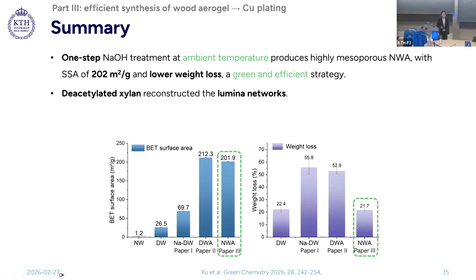Different from the reported wood aerogel fabrication studies, here we demonstrate that the deacetylated xylan migrates from the cell wall and reconstructs the lumina fibrils during the treatment. As the application demonstration, copper-plated wood aerogel shows favorable electrochemical performance due to the copper-coated lumina network and its mesoporous structure.